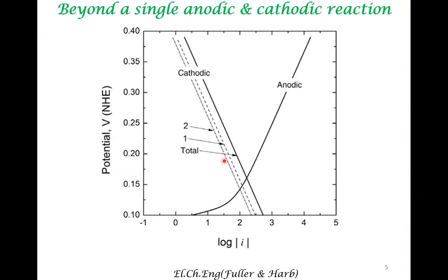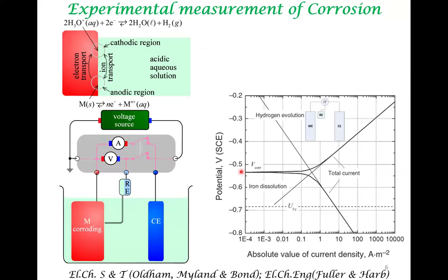So in this plot, we have two cathodic reactions, and the overall consumption of electrons via a cathodic reaction has to match the rate of generation of electrons from the anodic reaction. So it is possible to incorporate more than one reaction. It can be more than one cathodic reaction. It can also be more than one anodic reaction. But the overall concept of corrosion potential and corrosion current is not going to be affected.